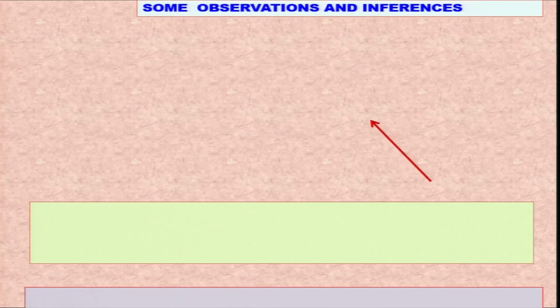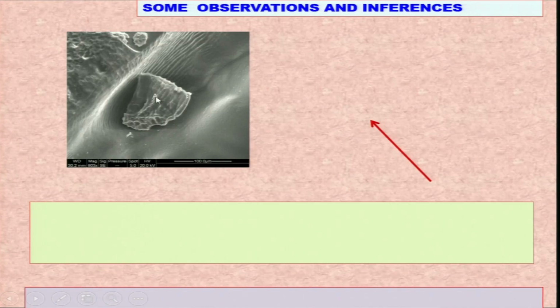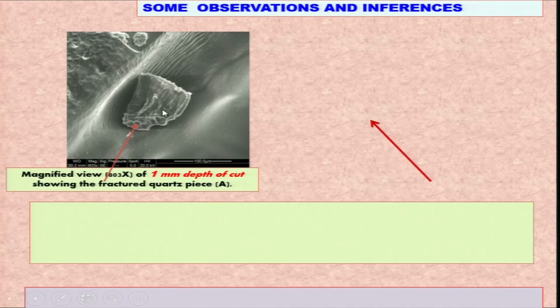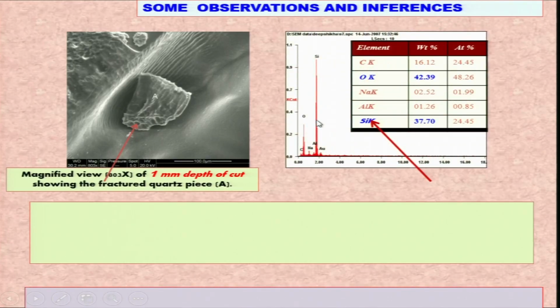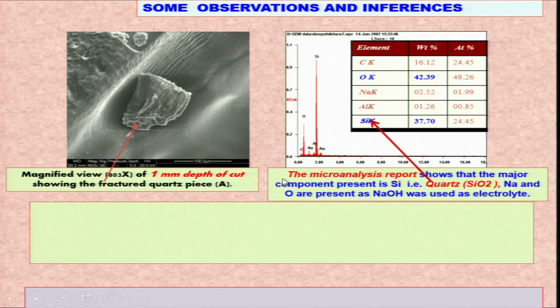Now, some observations and inferences. Here I have already mentioned that it is not only melting and vaporization, rather it is the fracturing also which is responsible for removal of material in electrochemical spark micromachining, and this is the magnified view of 1 millimeter depth of cut showing the fractured quartz piece shown over here. Now, you can see here the elements that were observed: weight percentage carbon 16, oxygen 42%, sodium 2.52, aluminum 1, and silicon 37%. The microanalysis report shows that the major component present is silicon, that is quartz, silicon oxide, SiO2, and sodium and oxygen are present, as NaOH was used as the electrolyte.